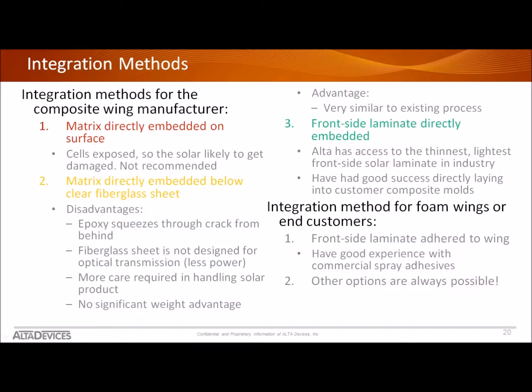And the first thought is, well, you just take the solar matrix and you embed it in the surface, which we consider a pretty high-risk solution. The cells are exposed. They're likely to get damaged when you integrate if you're not familiar with handling the material, and so it's not recommended.